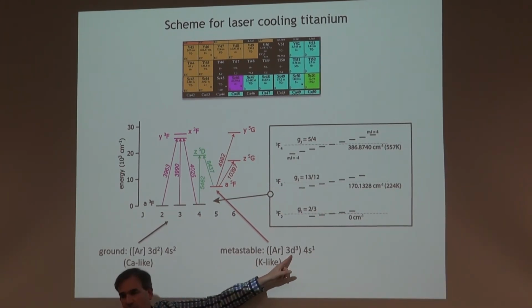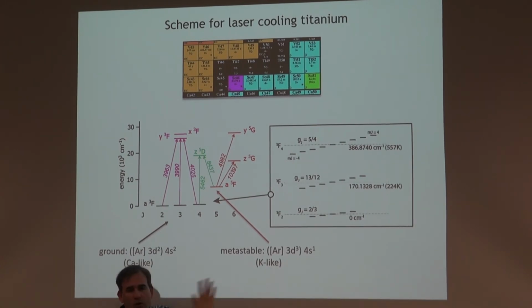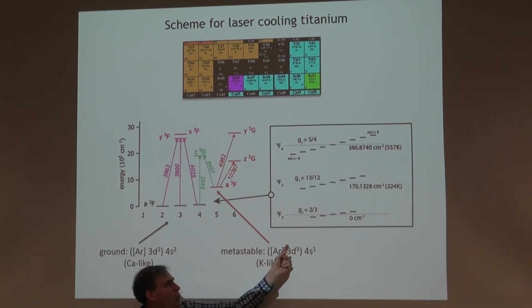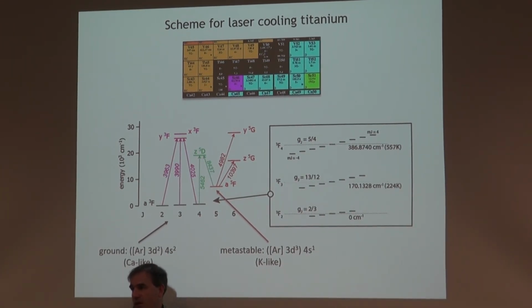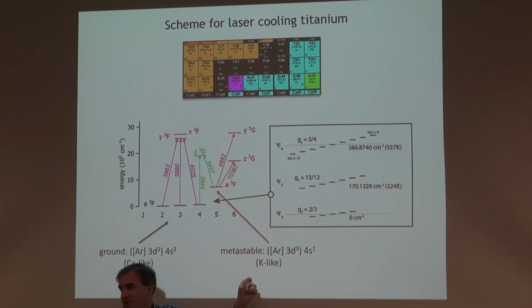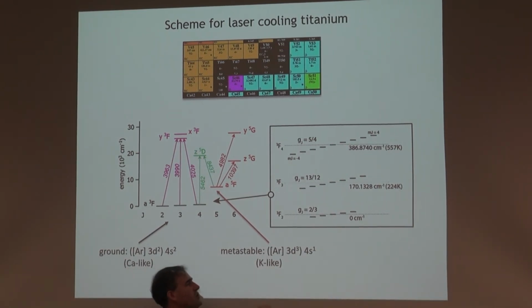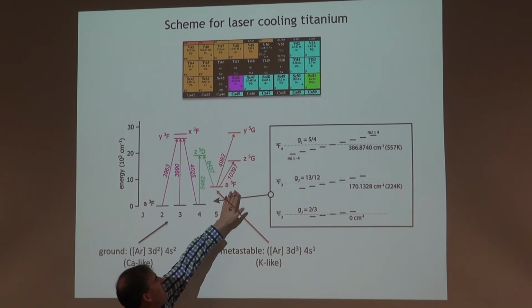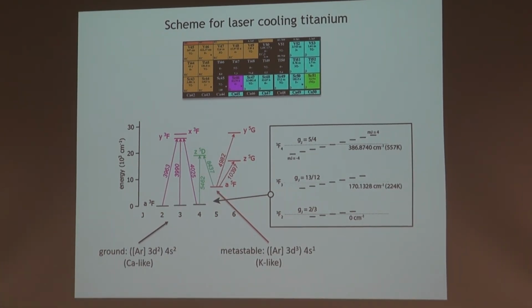So titanium also contains a lot of metastable states with this other low energy configuration, where one of the s electrons moves into the d orbital. Remember that the s and d orbitals are fairly equivalent for the transition metals. And in particular, if we look at the metastable state where these core electrons and also this s electron are all spin polarized, then we're in a fortunate situation that the spectrum out of this state is almost like the spectrum of potassium now. It's as if we have just a single valence electron, this 4s electron, which you can drive in a 4s to 4p transition, and decay downward has to respect all the spin that's stored inside of this system, so it will always come back to the same starting point. So in particular, this a5F5 level is a great state for laser cooling.